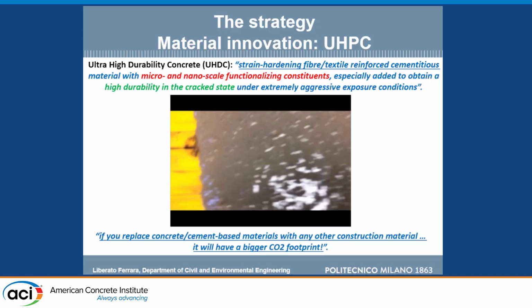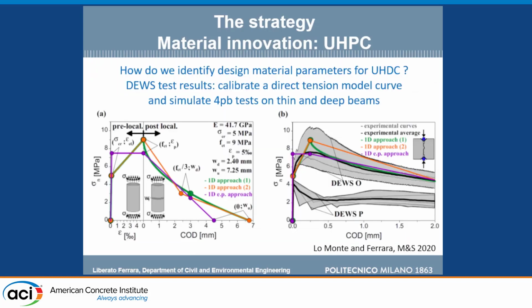So what we wanted to see was the strain hardening capacity in tension and the durability in the cracked state, which was what was matter. We achieved the strain hardening capacity. You can see there we have a strength of about 7 to 8 megapascal, but the strain hardening response up to 0.5% deformation, which is well beyond the yielding of conventional steel in reinforced concrete structures.